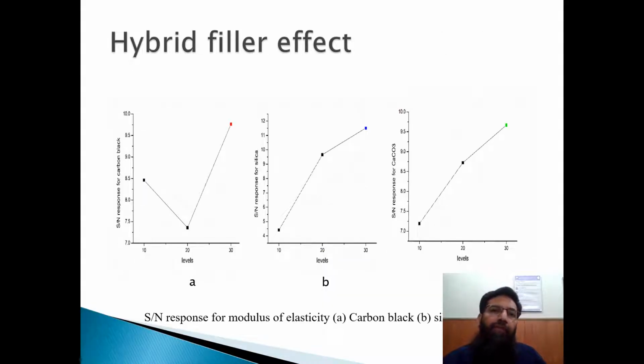Similarly, we also check the effect of the different hybrid loading of the filler. We had the carbon black, we had the silica, and we had the calcium carbonate. Carbon black and the silica both are the nanofillers. Calcium carbonate, that's not the nanofiller, but it's in the micron size. But mainly to make the compound cost effective, we have to add the calcium carbonate as well. So in this you can see the effect on the modulus as we increase the loading of the filler, the modulus of the compound increases.